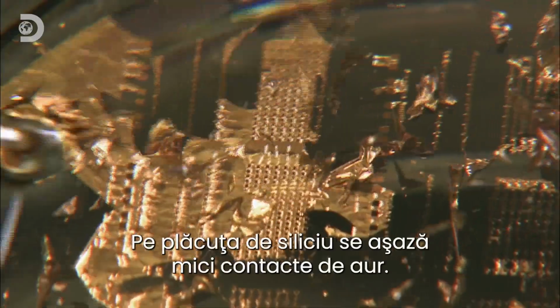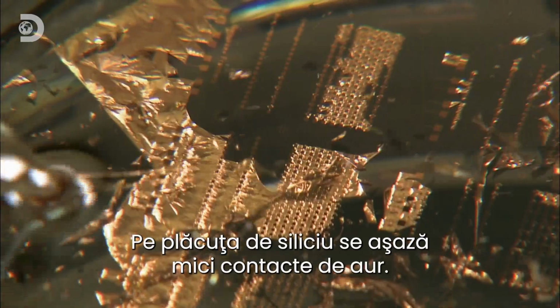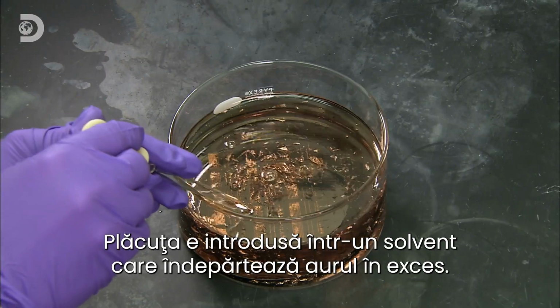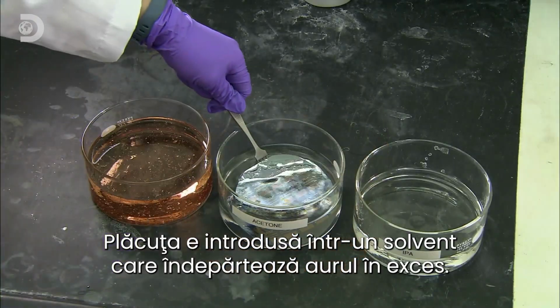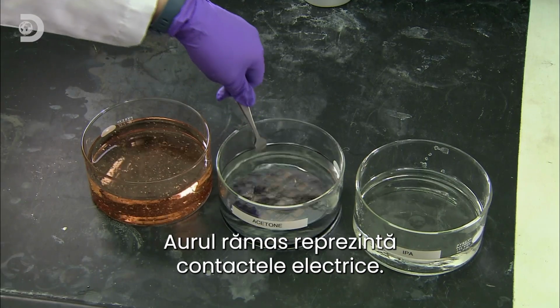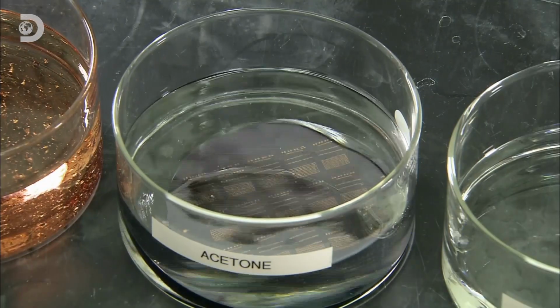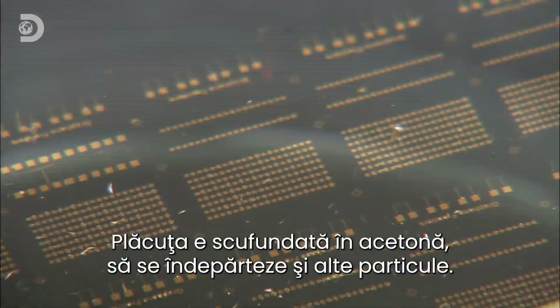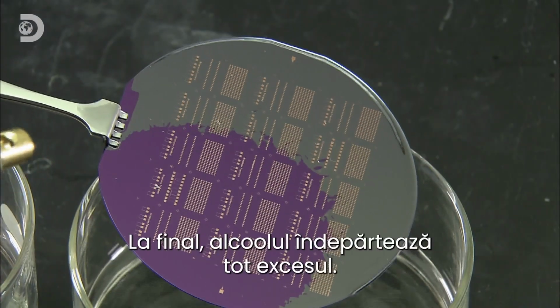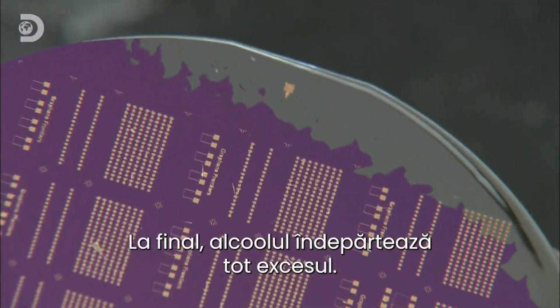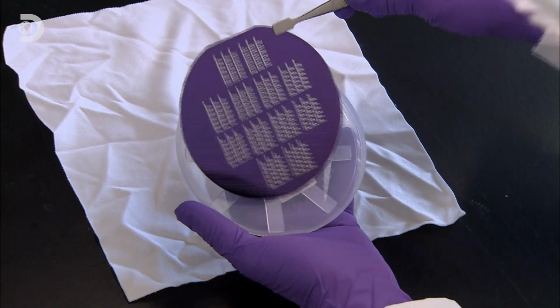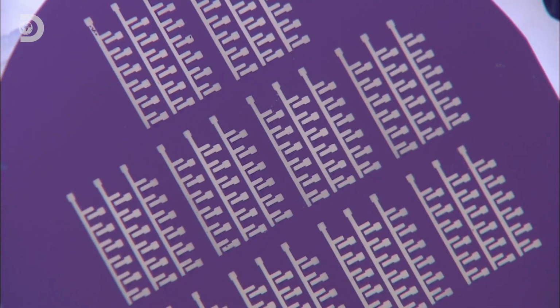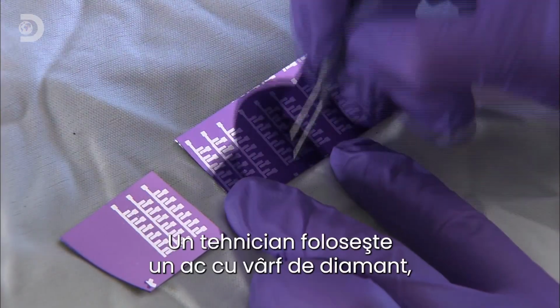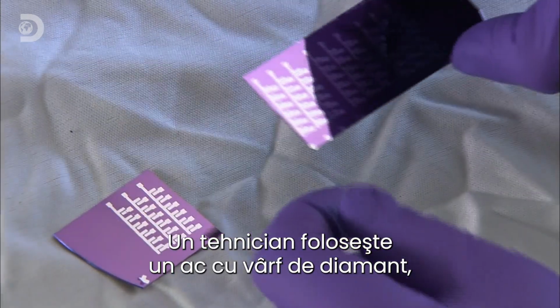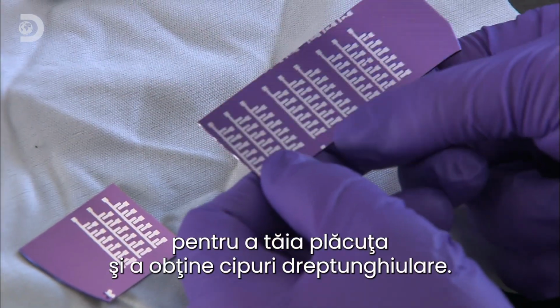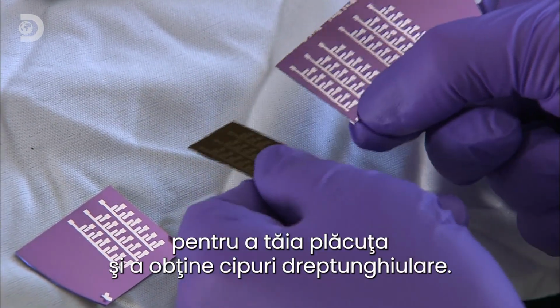Next, tiny gold contacts are applied to a silicon wafer and submerged in solvent to rinse off the excess gold. The remaining gold bits on the wafer are the electrical contacts. A dip in acetone cleans off more of the lingering loose flakes. And a final rinse in alcohol removes the rest. Using a diamond-tip scribe, the technician scores the silicon wafer and breaks it along the score lines, creating rectangular chips.